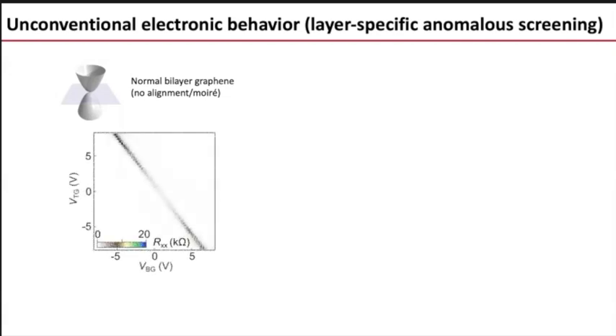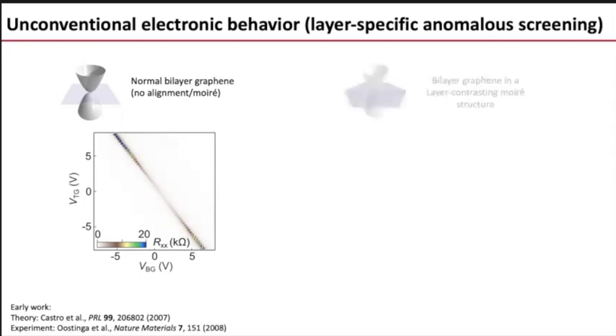Okay, so if you have regular bilayer graphene with no alignment to the hBN, and you measure the resistance as a function of back gate and top gate, then you see this diagonal line, where this diagonal line is actually the charge neutrality point, the resistance peak, okay? Resistance is low in this region, high in this region. And it's high here, and it gets higher when you go away along this charge neutrality line when you apply a displacement field, because a band gap opens here when you break the symmetry between the two layers. This was first theoretically proposed by Castro and collaborators, and measured by Alberto Morpurgo and collaborators, and this has been seen thousands of times. Now, let me show you what happens if you have bilayer graphene in this layer-contrasting Moiré structure, okay?